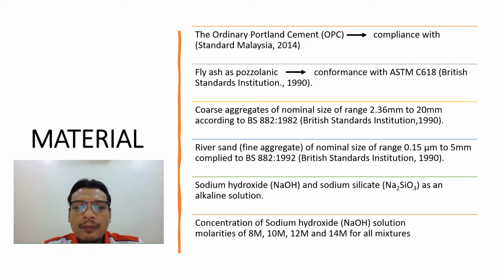The mixture of sodium hydroxide and sodium silicate was used as an alkaline solution. The concentration of sodium hydroxide was varied at molarities of 8, 10, 12 and 14 molarities for all mixtures.